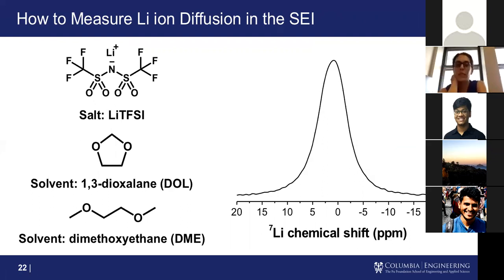So if we take a look at our lithium NMR, just as is, we end up getting this one singular peak sort of around 0 ppm. We see our lithium metal peak around 250 ppm, but I'm cutting that off for now. I'll show it to you later. So this doesn't look like we have a high diversity of things in our SEI. It just looks like we really have one thing.